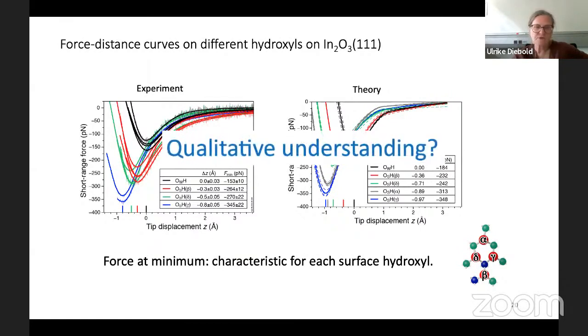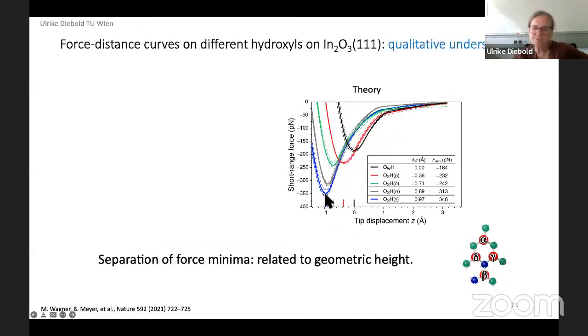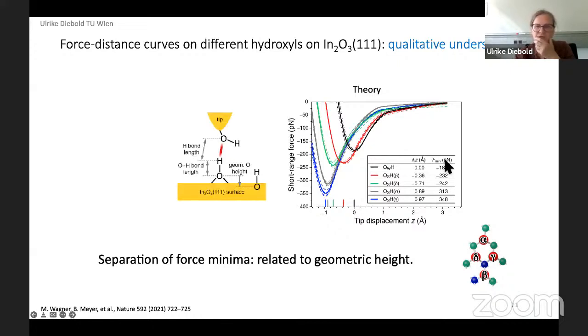So it's really two things we look at. We look at the minimum, the position of the minimum, the tip displacement. So where is this minimum when you go on the different hydroxyls, and also the depth, how deep is this minimum? So these are the two characteristic values we look at, the delta Z and the minimum. The delta Z, so 0 is arbitrary. We just take this one. And then it's just when you come in with the tip, it makes some sort of hydrogen bond between the last oxygen atom on the tip and the proton on the surface. So it's like a little temporary water molecule is formed.